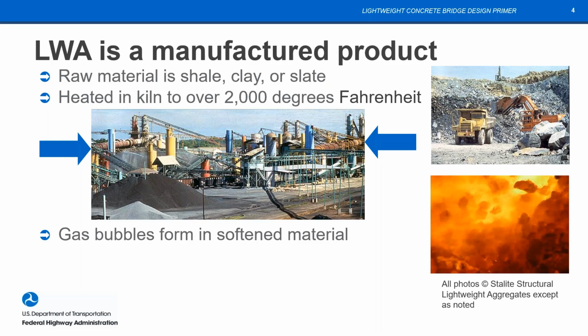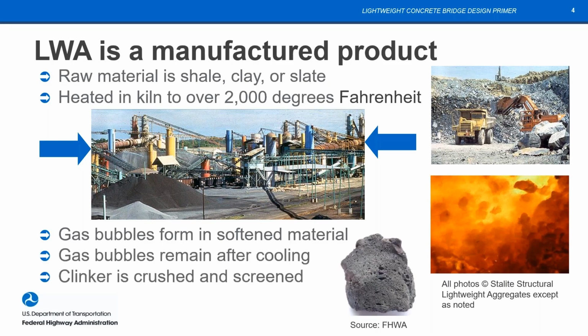In those kilns, the heat is fed in at the bottom, the raw materials at the top. The material gets soft as it gets down to the bottom. We don't melt it, but it's just softened. As you can see, it turns red hot. And then gas bubbles are evolved within that material. As that material comes out of the kiln, it's cooled, the gas bubbles remain, and the clinker is then crushed and screened. There are a few other sources of lightweight aggregate available, but my discussion is going to be limited to lightweight aggregates that are produced using rotary kilns.